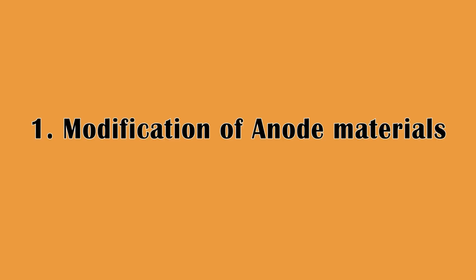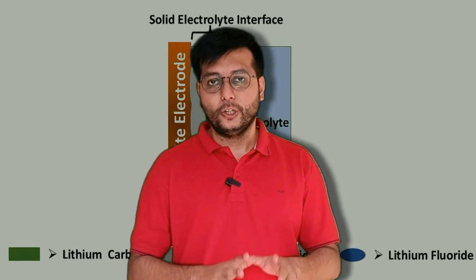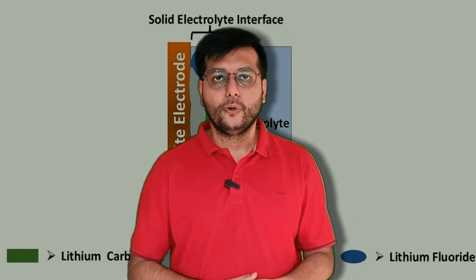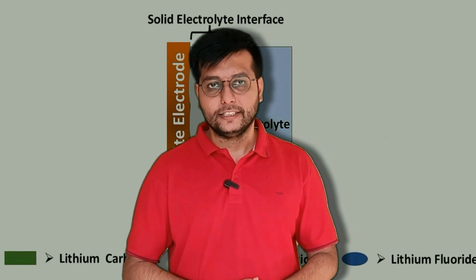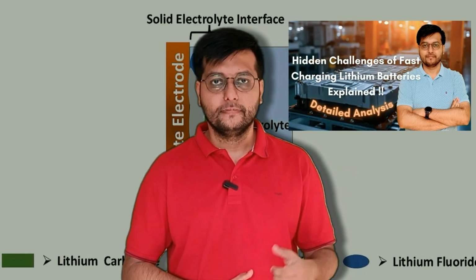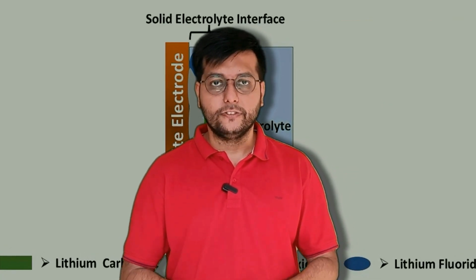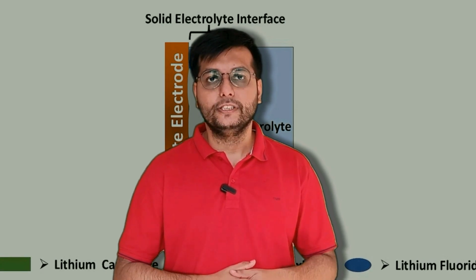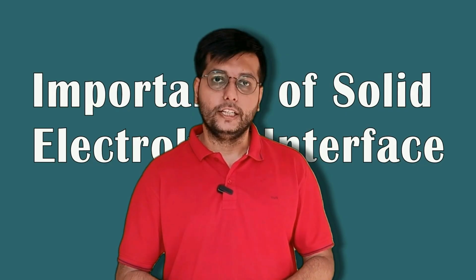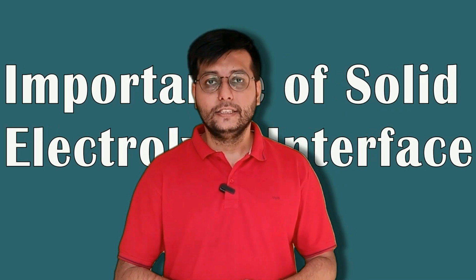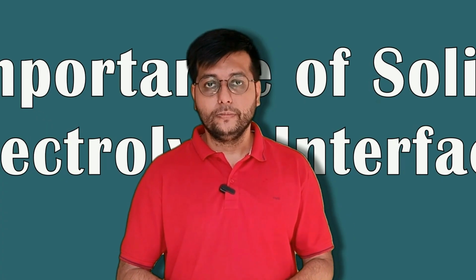First, modification of the anode materials. The solid electrolyte interface, or SEI, is a layer that is formed on the surface of the electrodes as discussed in the previous video. The SEI has much significance in controlling the battery's thermal runaway because it controls the chemical reactions on the electrode surface and hence prevents the electrodes from overheating. Thus, the stability of the SEI is very important.